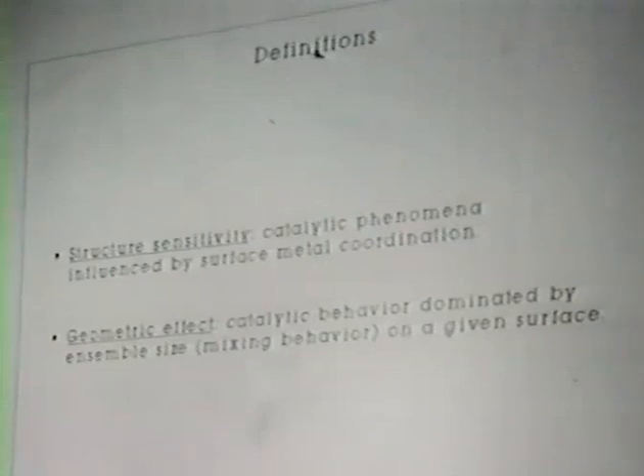I think part of the discrepancy is due to a semantic problem. Let me throw out some definitions I will be using in this talk. What I mean by structure sensitivity is that the catalytic phenomenon is strongly influenced by the surface-metal coordination — for example, reaction rates varying on different crystal planes on single crystals, or on supported catalysts on various sites on the metal. Edges and corners tend to be different from low-index planes.